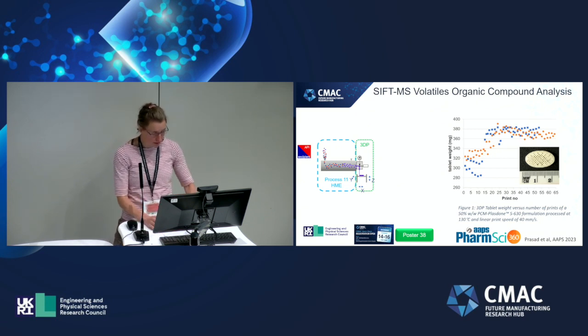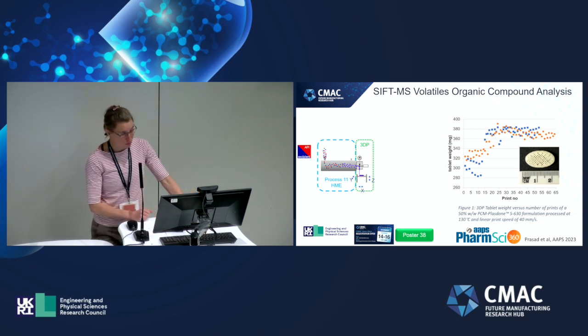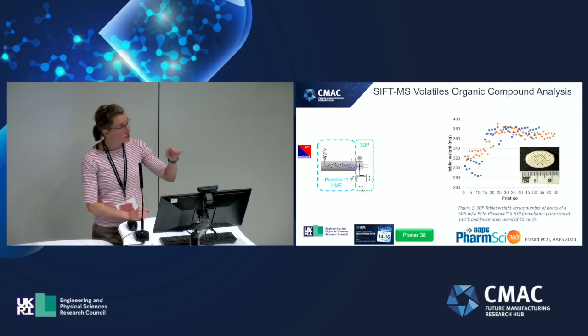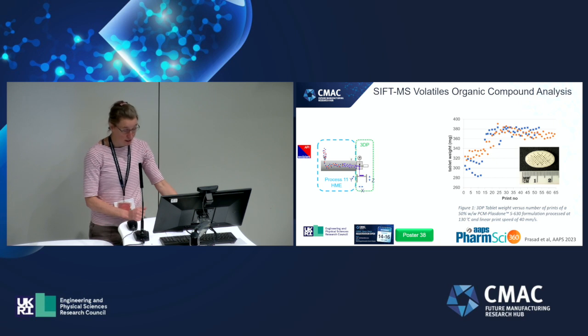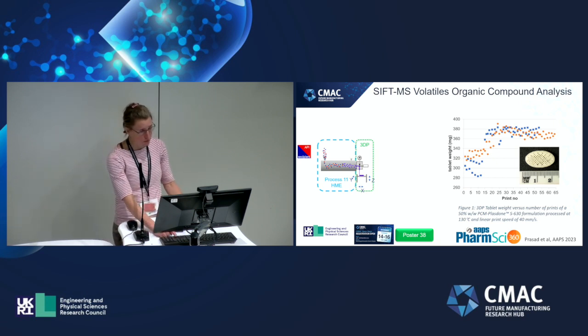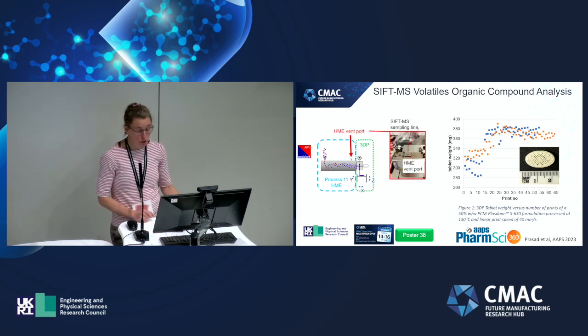This is a very recent activity. For some of you that were at the last open day, I showed the graph on the right-hand side, which relates to the tablet weight changes that we observed over the course of a manufacture. So we saw an increase in weight, which then stabilized and remained quite stable there throughout the course of the manufacture. So we wanted to investigate this, and we set up the hot melt extruder with the SIFT MS system